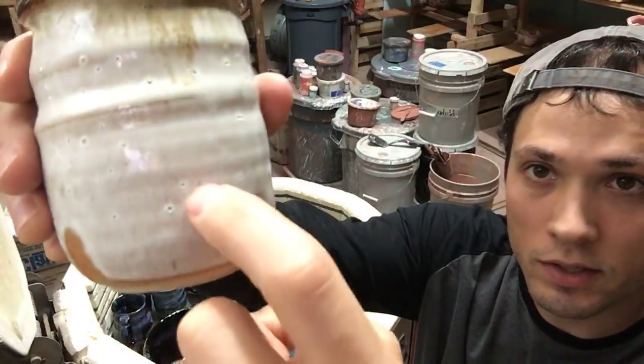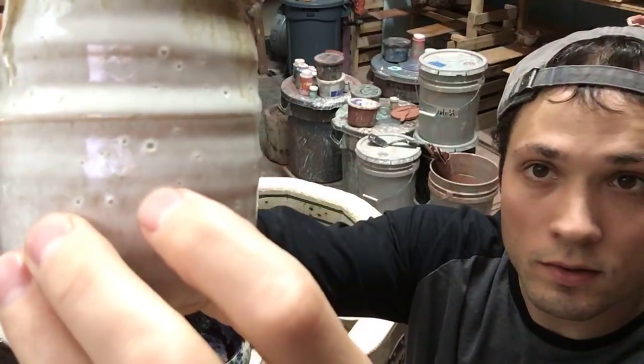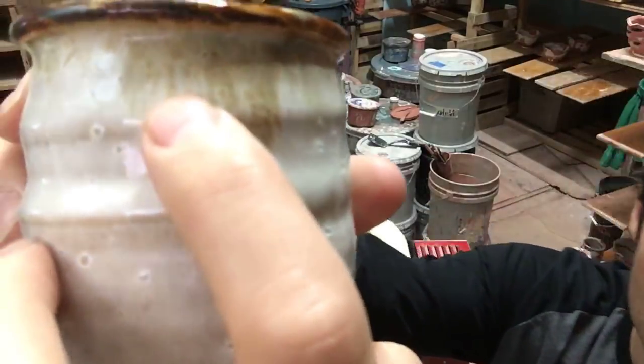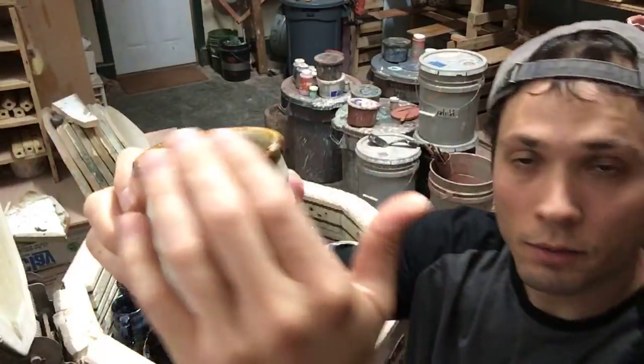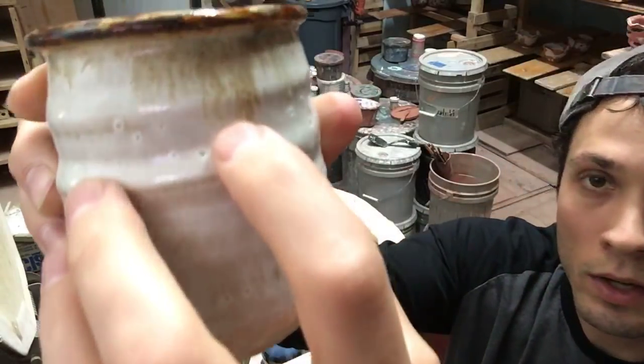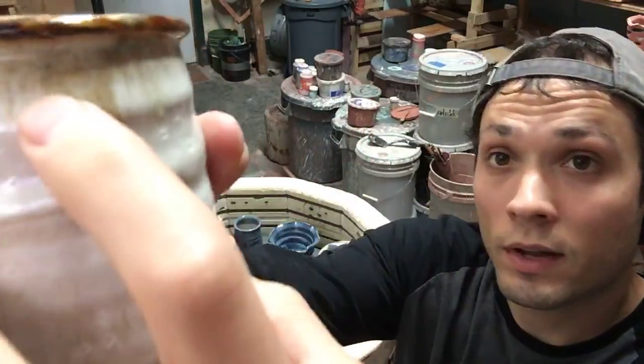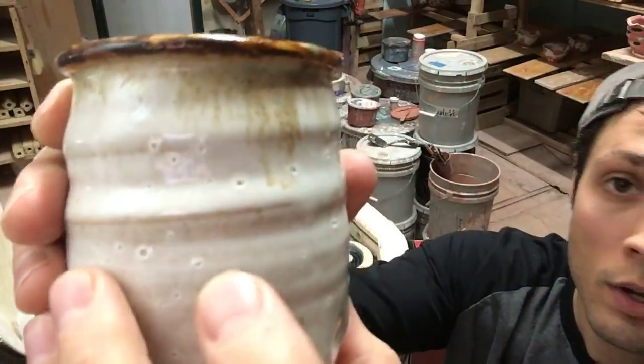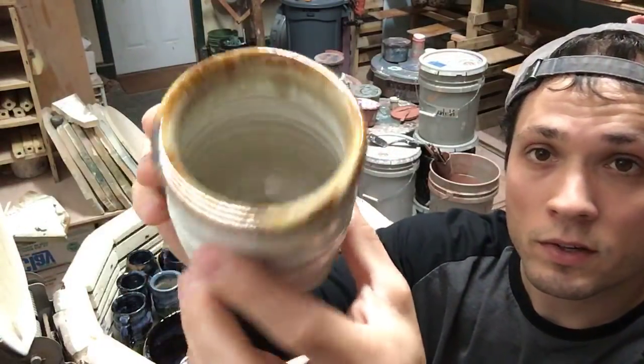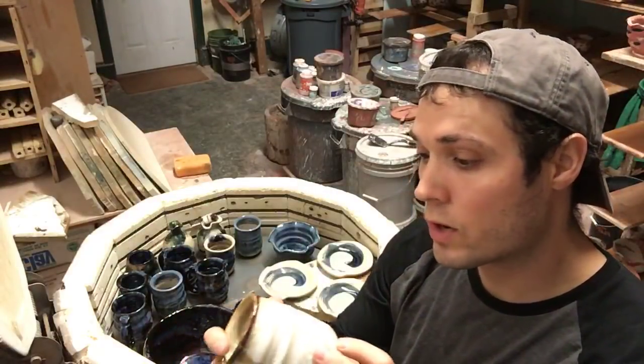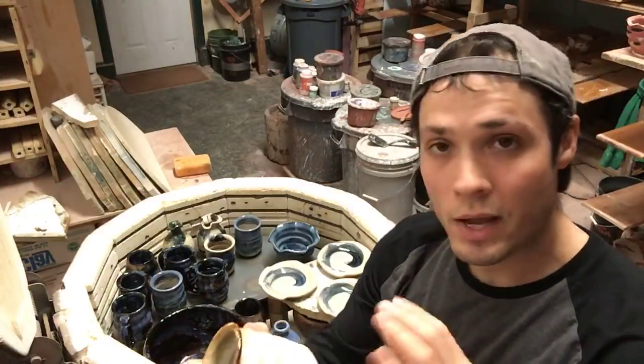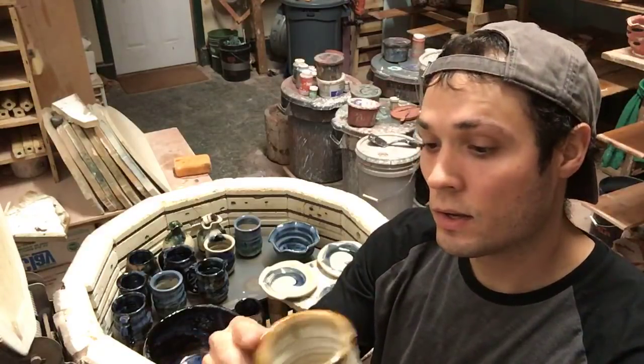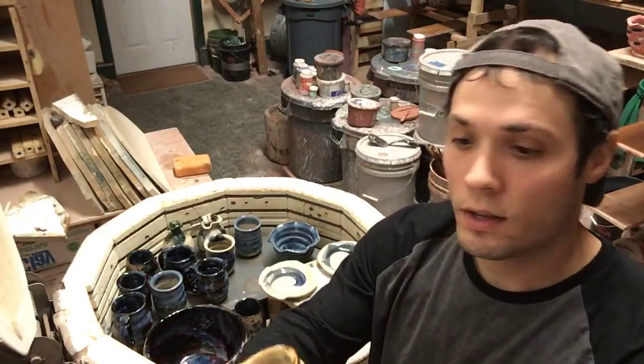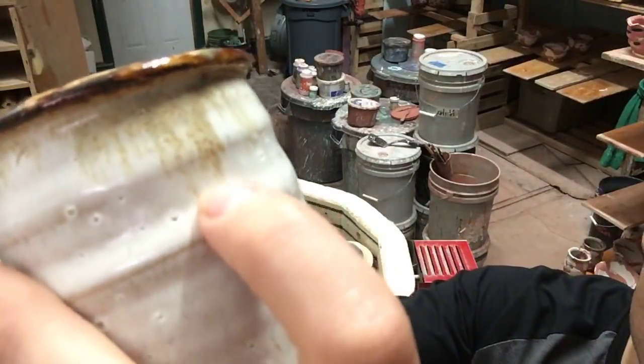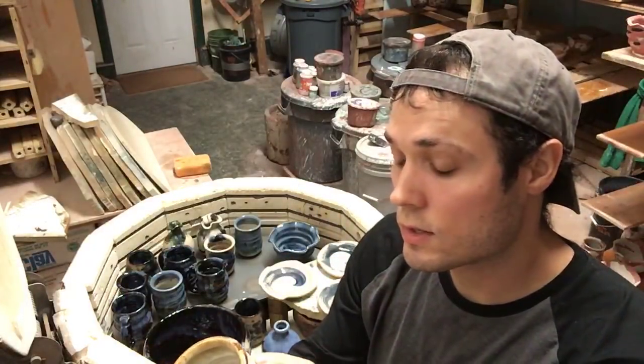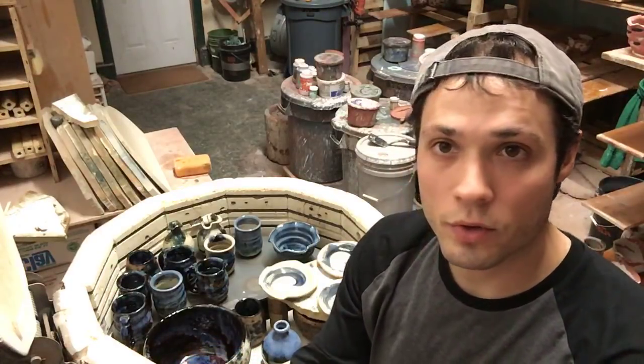Okay, so this pot, there's a lot of things we can tell from this pot. It fluxed, it's nice. You can see that this bubbling is not so nice. See the speckling here? I put just a little bit of iron on the rim. It dripped really well. Made some crystal formation. And so nearly everything about this is exactly what I'm going for. It's a gloss, but it's a little bit semi-gloss. It's not like a high gloss. And the color is great. The crystal growth, again, that's really exciting. You don't get that in most glazes, but I've seen a lot more crystal growth in wood ash glazes.